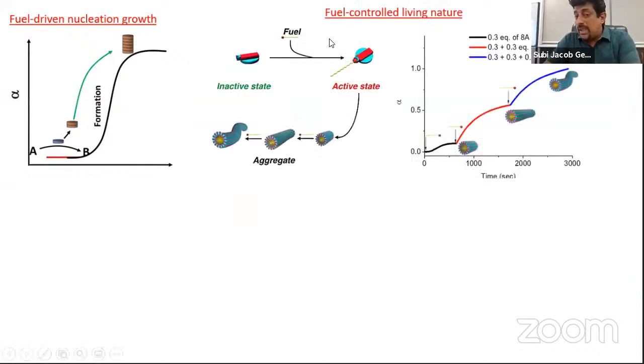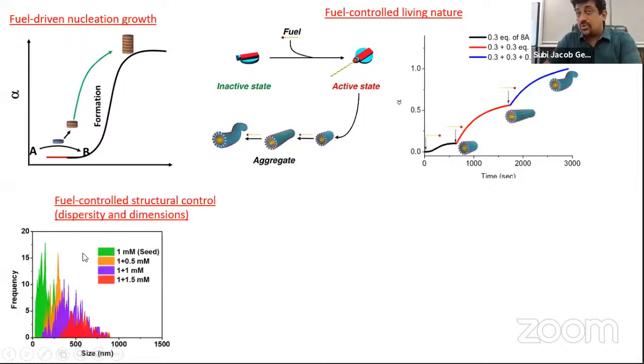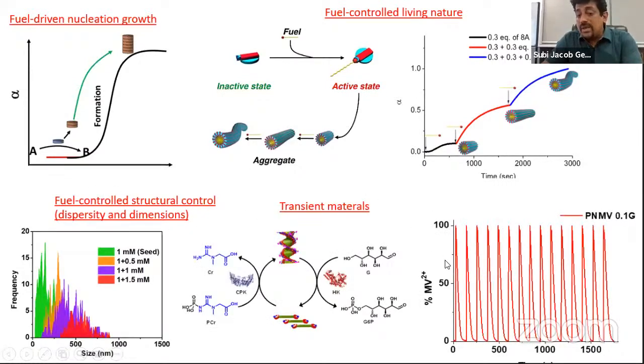So as a result, we could make a kind of seeded polymerization, thereby we can control the degree of polymerization. We can get a dispersity which is close to 1.1 in these structures because fuel controls the controlled growth. And also we can make transient material, out of equilibrium materials. So this is something which we have been continuing in our group.